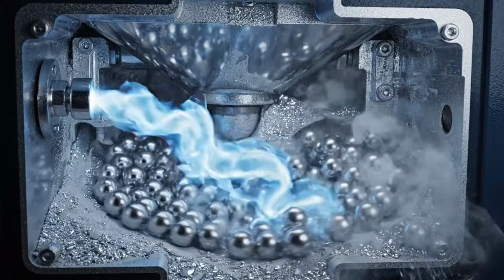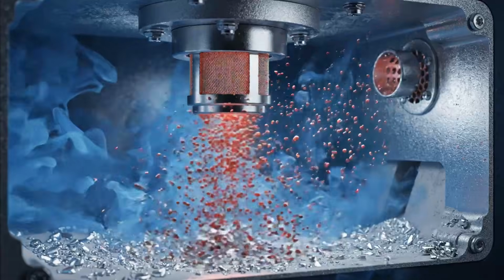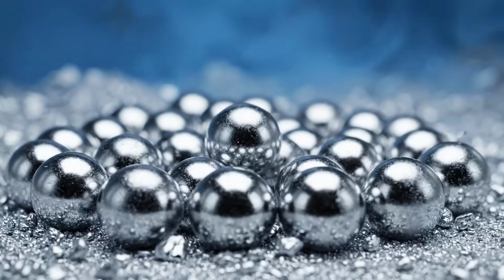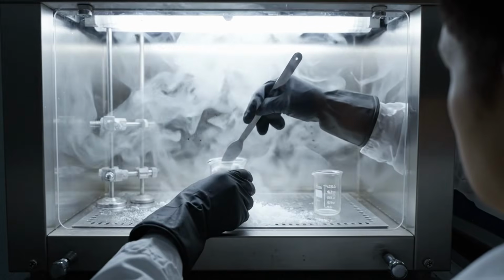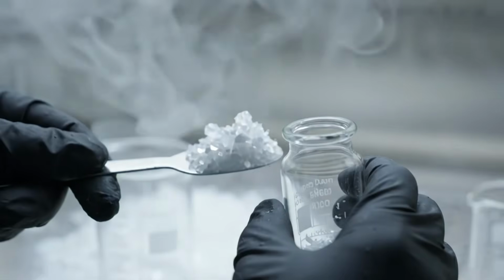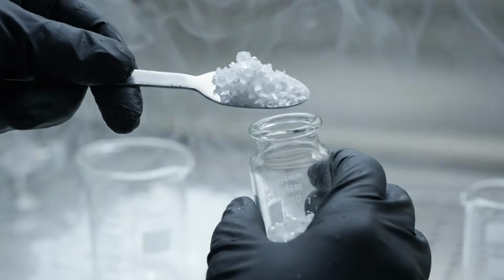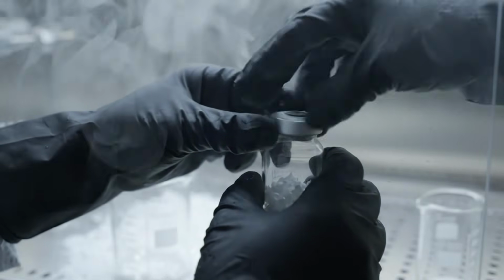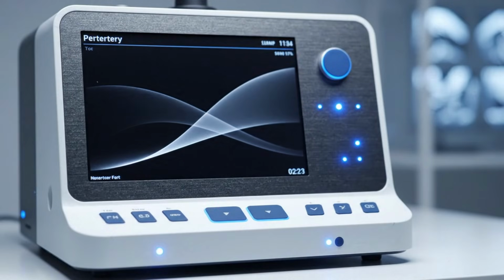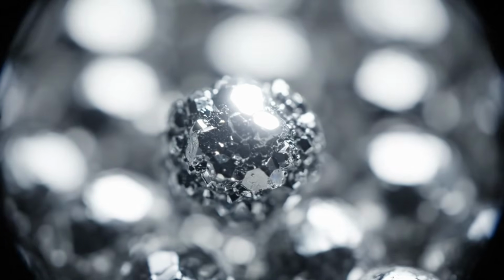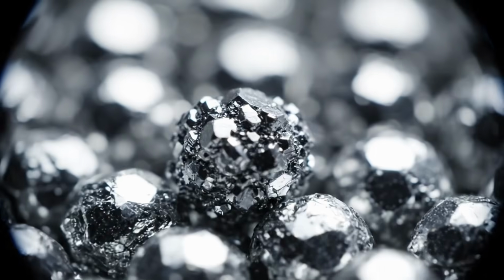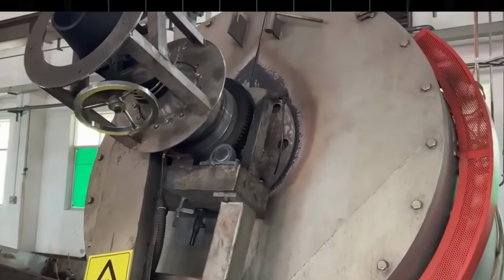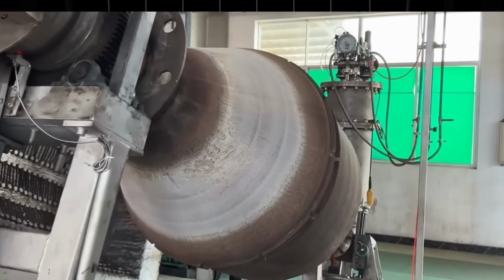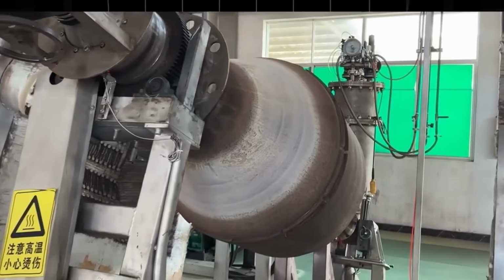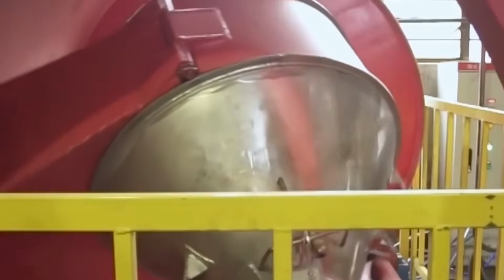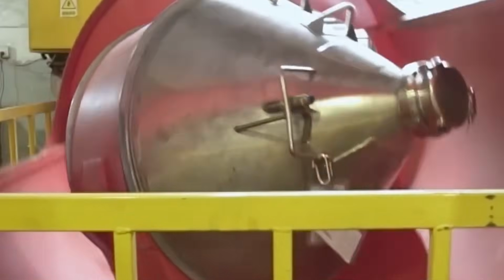After sintering, many parts undergo further heat treatment. This process stabilizes the crystalline structure and improves properties such as coercivity. The material is then reheated to lower temperatures and subsequently cooled in a controlled manner. The block appears almost unchanged, but internally the grain boundaries, metallic phases, and crystalline orientation are adjusted to better resist demagnetization. It is a silent but crucial stage. Upon exiting the furnace, the sintered blocks already possess an internal structure prepared to become powerful.